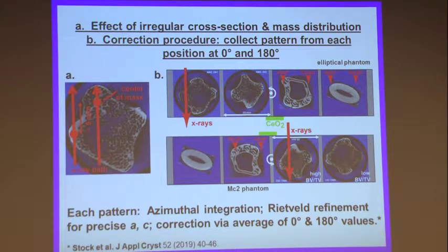Now, the problem we have when we want to do position-resolved scattering is our center of mass might be here, or in a different position might be here. A distance separation between the 0 position from which we were obtaining diffraction, differing by 5 millimeters, is not going to give us a precise lattice parameter. It's going to give us a problem. So we have to correct for that.